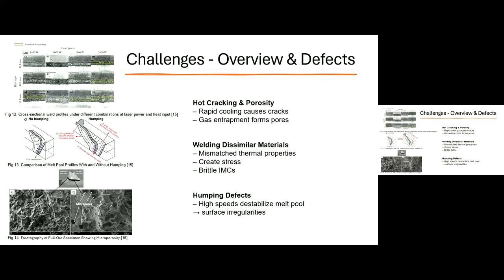Okay, now we're going to look at some challenges, some defects that we see in laser welding. First one is hot cracking and porosity. We know how hot cracking happens. It happens when rapid cooling causes cracks. And porosity is gases stuck in between the pores. There's also, when we weld dissimilar materials, we get mismatched thermal properties, which creates unnecessary stress, and also brittle intermetallic compounds. There's also humping defects, which I was talking about. When we're welding at high speeds, it destabilizes the melt pool, and we get surface irregularities because of it.